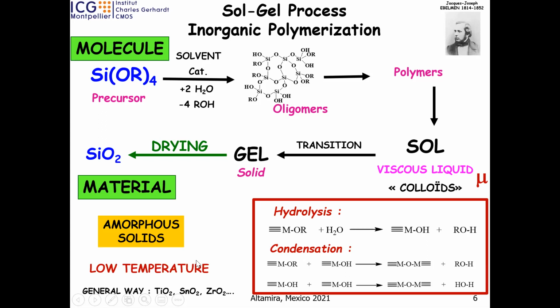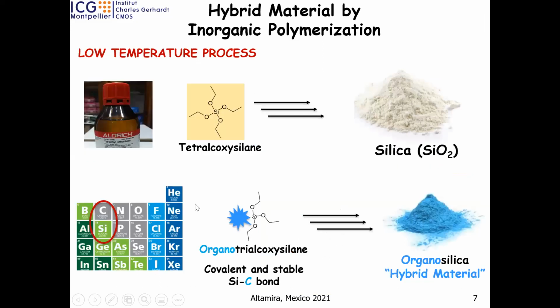In general, we obtain an amorphous solid, and it's a general way, as I said before. The main advantage is this process can take place at low temperature, even at -20, it works. It's not necessary to heat. Sometimes we heat a little bit to accelerate, but it's kinetically controlled, not thermodynamically controlled. When you have your catalyst, it's possible to make hydrolysis and polymerization.